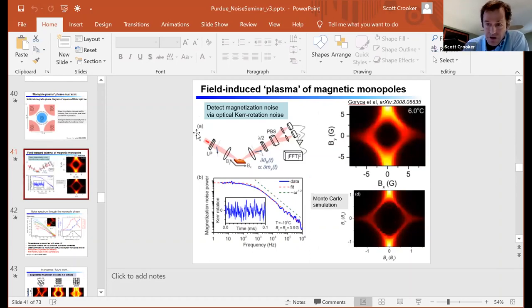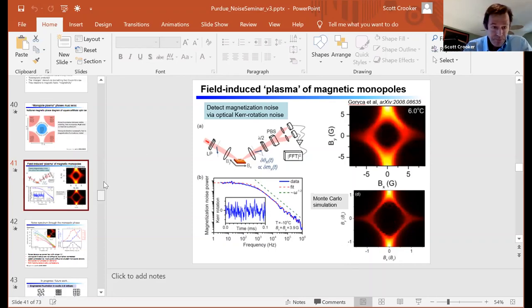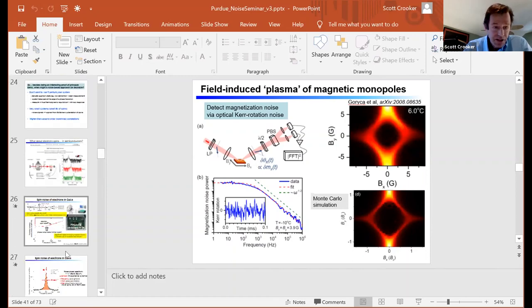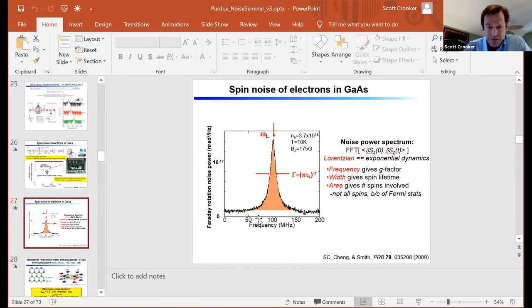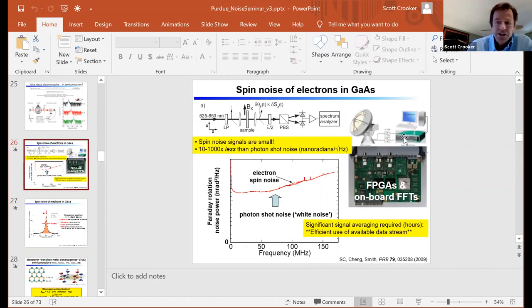In all the experiments I've described thus far, we're just using a CW laser and we're relying on the speed of the detectors to give us our ultimate bandwidth. In the case of the spin ice, we were measuring out to only 1 megahertz, but we stopped there because there was really no signal beyond that. Here, the challenge was getting really low frequencies, because everything in the lab has low frequency vibrations and fluctuations. For the semiconductor systems, such as gallium arsenide, we were able to go out to something like 1 gigahertz, and in that case it's limited by the speed of the digitizer. So it would be difficult to get faster than 1 gigahertz using CW lasers. That's the best answer to your question, but that's really a technical problem.